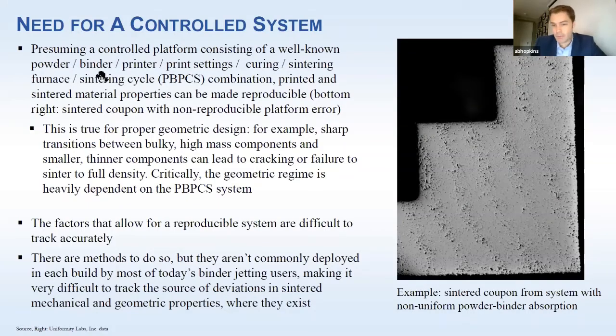And the binder powder interactions are really important. I talked about powder. Naturally denser powder can do a lot of good. Finer particles have higher mobility, so they can sinter more at lower temperatures, but then they don't spread very well. The rheology is poor. The cohesion is too high. Lower cohesion powder with finer particles is a great idea. I'm very subjective. That's one of the things Uniformity Labs does, but it works. So binder powder interactions are important.